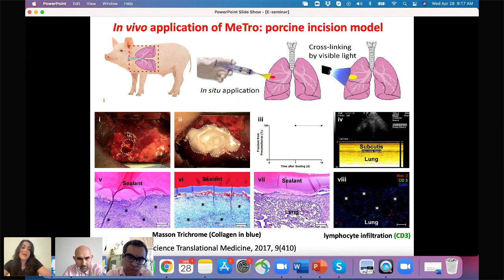weeks. And here, in this picture, you see the defect that we created on the lung. And then here is the polymer that photopolymerized on the defect site. We did ultrasound every 2 days to ensure that there is no leakage from the defect. And with the histology and immunostaining analysis, we show the tissue repair over time, and we didn't observe inflammation around the biomaterials. So with this experiment, we confirmed that MeTro is effective to seal a smaller size defect on